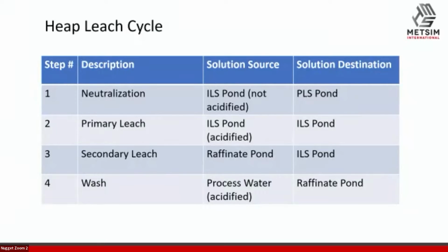Secondly, then we'd focus on the primary leach. We would again pool ILS, except this time the ILS is acidified and pretty strong, 50, 60 gram per liter. Those that work in copper heap leaching have no idea what that would look like. So pretty strong stuff. And that reports right back to ILS. So a closed loop on the primary leach. Follow that with a secondary leach. We're pulling from raffinate now, again acidifying, 50 to 60 gram per liter, basically leaching everything that we can, sending that into ILS. And then a wash.